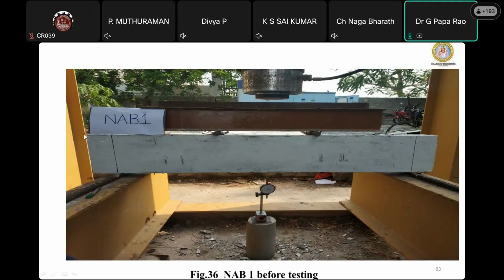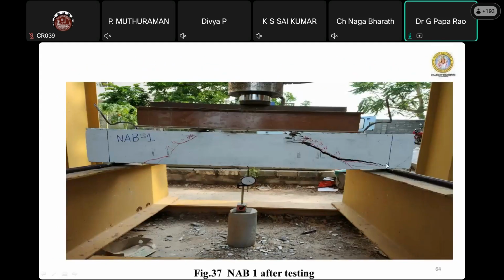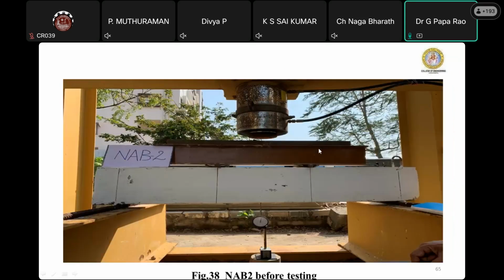And the NAB1 beam was 100% natural coarse aggregate, 0% recycled, and this beam was not provided any shear reinforcement. Deliberately, we have done this to make sure of the beam's shear behavior. So this is the observation after testing: the beam failed in shear mode of failure.